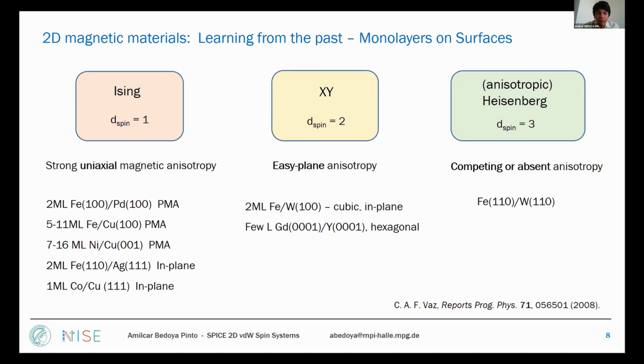One thing I would like to mention here is that for the Ising case, of course, you need a strong uniaxial magnetic anisotropy. And usually in the 2D materials community, it has also been said that the Ising type must have an out-of-plane anisotropy. That is not strictly correct, because an Ising type can also be an in-plane magnetized system with a strong uniaxial anisotropy, for example, given by magnetocrystalline anisotropy. So here you will find 2 examples of this kind.